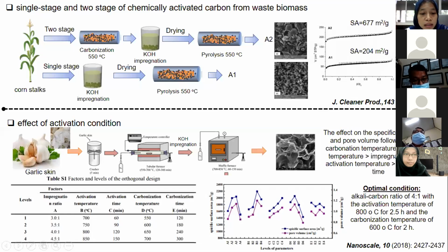There is the effect of the impregnation ratio. With the ratio increase, more carbon can react with the activator, generating more pores, and eventually increasing the specific surface area and the pore volume. When the ratio exceeds the optimum point, excess KOH reacts with the carbon atoms, causing excessive ablation of the carbon. The carbon skeleton around some micropores collapses, making some micropores combine to form mesopores or even macropores, leading to a decrease of the specific surface area and pore volume of the carbon.